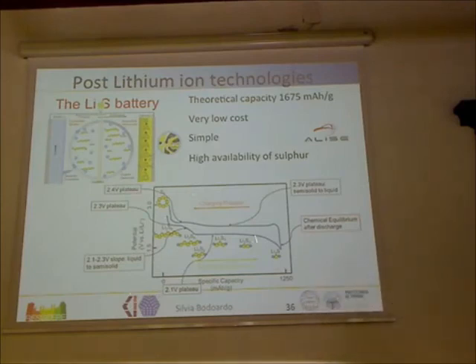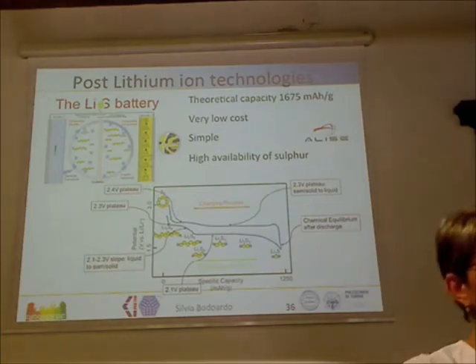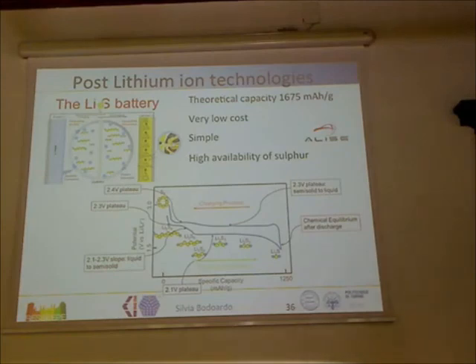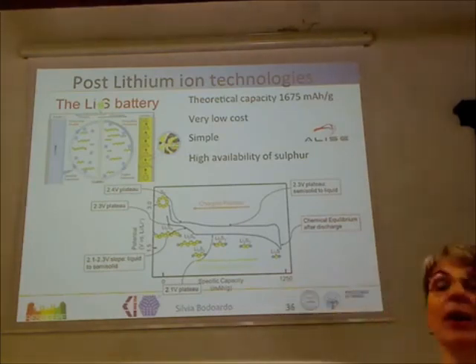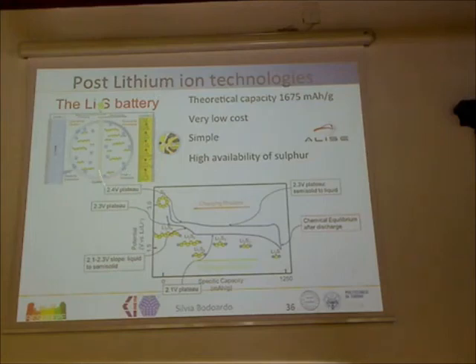The reaction occurs through several steps. The first step is that in which sulfur, that is mainly a solid, a sort of polymer composed of rings, opens, and when it opens it becomes soluble. So it goes in solution, it starts to reduce, forming some intermediate salts, all soluble in solution, and then it precipitates at the end as lithium sulfide. So the reaction occurs through several steps, and some of these steps are inside the electrode, some of the other steps are in the liquid. And if these polysulfides move and arrive at the anode, they react directly there.